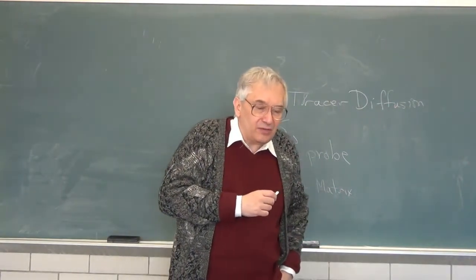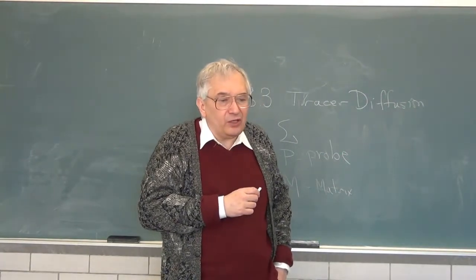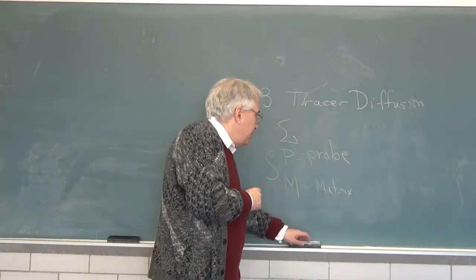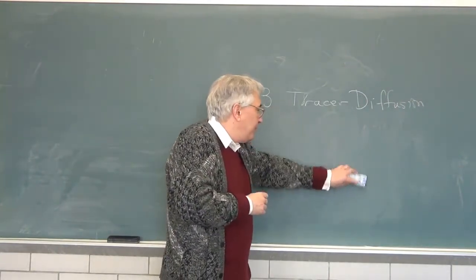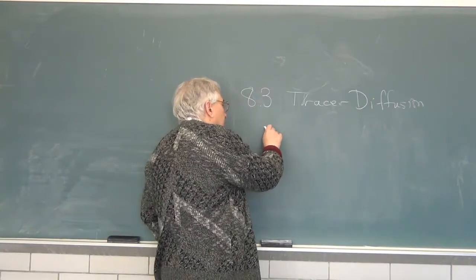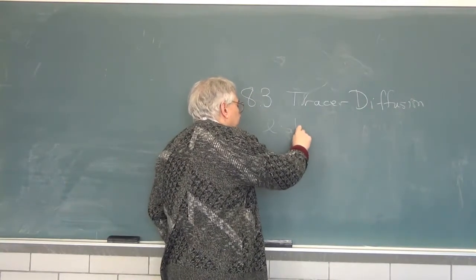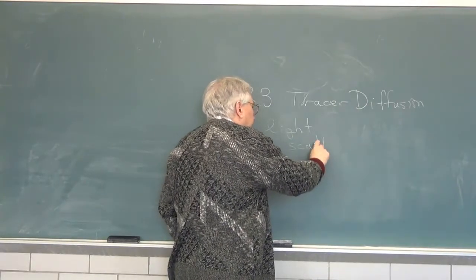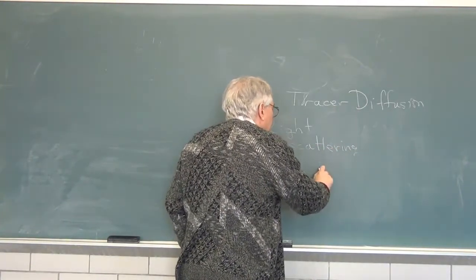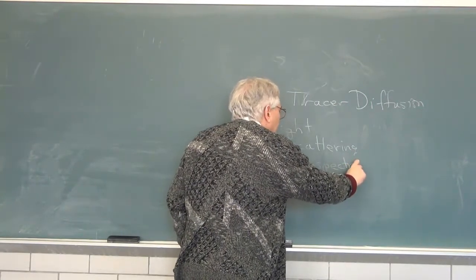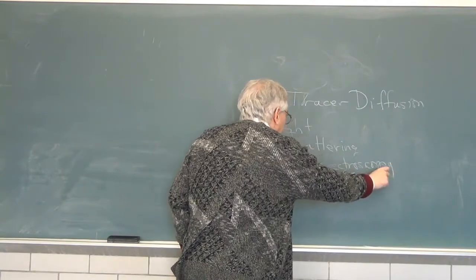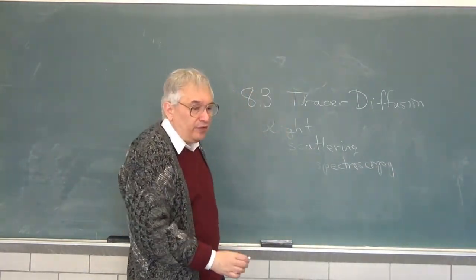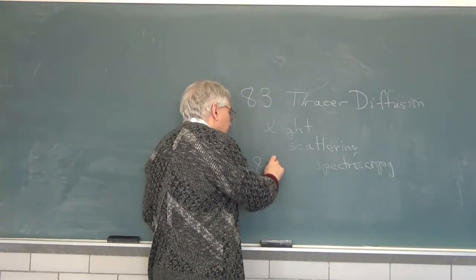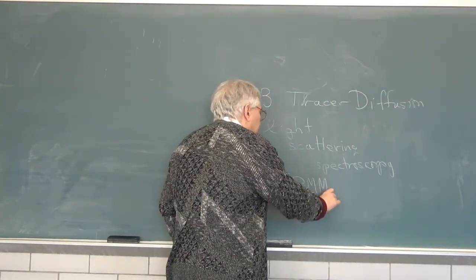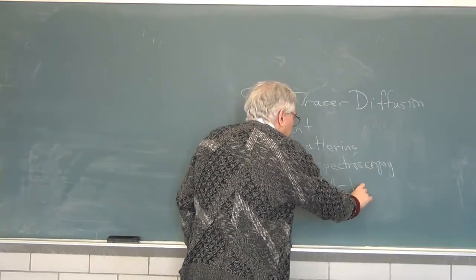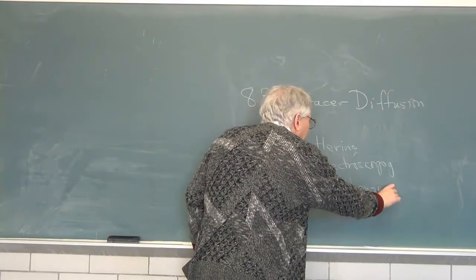And the question is, well, that's very nice, so how are we actually going to do this? Well, the main answer is you have to make the matrix invisible. One choice is to use light scattering spectroscopy, which gives us a measurement of the diffusion coefficient, and we use the trick that if we have a polymer, for example, and we'll start off with figure 8-15, polymethyl methacrylate, and we are in a solvent, to be precise, benzene, which is pretty nasty to work with, and you should treat it with great respect.